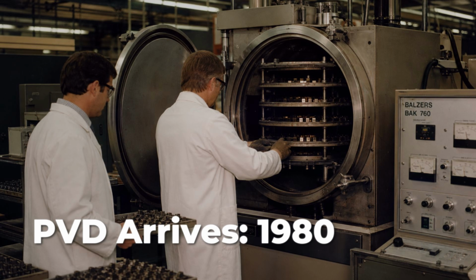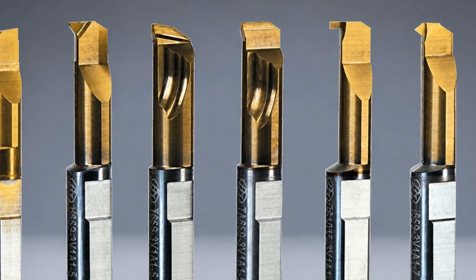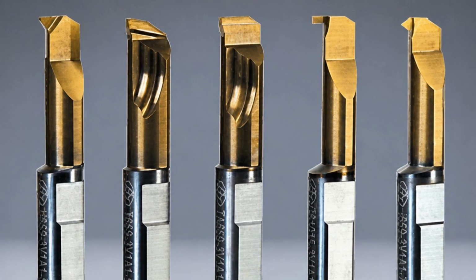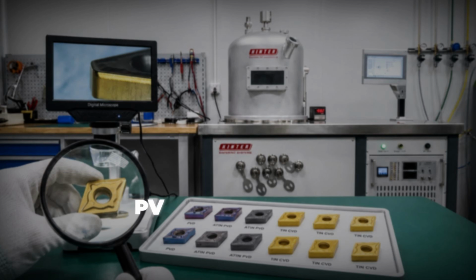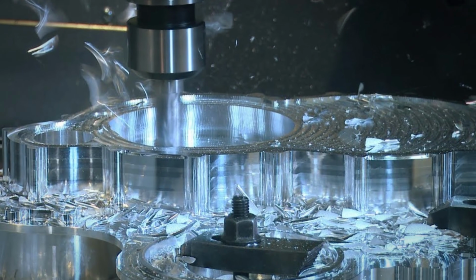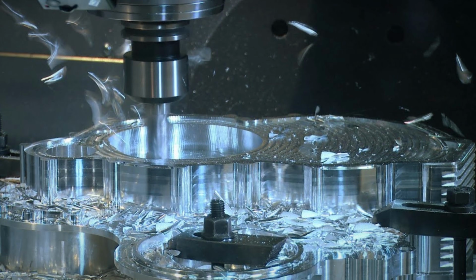Physical vapor deposition followed commercially around 1980 with the gold titanium nitride finish every machinist recognizes on sight. PVD runs below 500 degrees Celsius, keeps edges sharp and substrates tough, and leaves compressive stress in the film, so it took over sharp-edged solid tools and interrupted cuts.